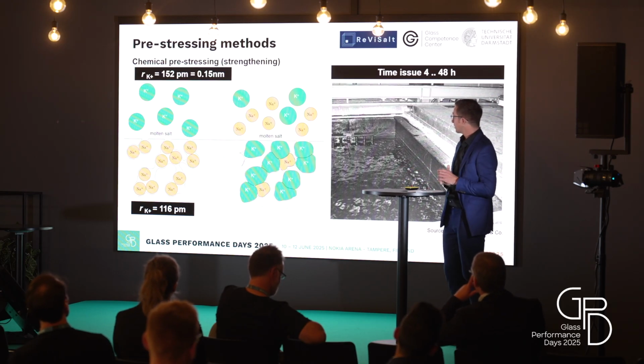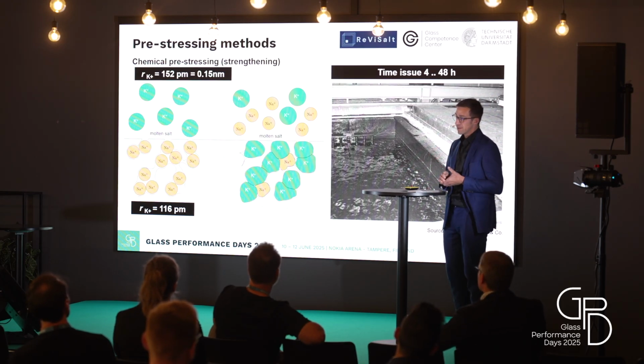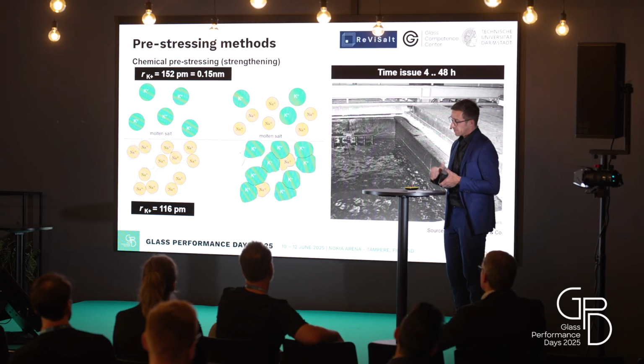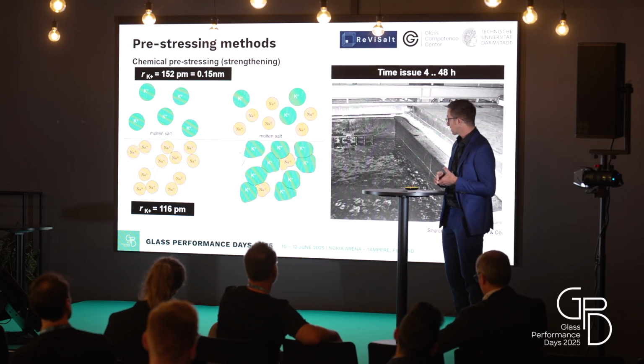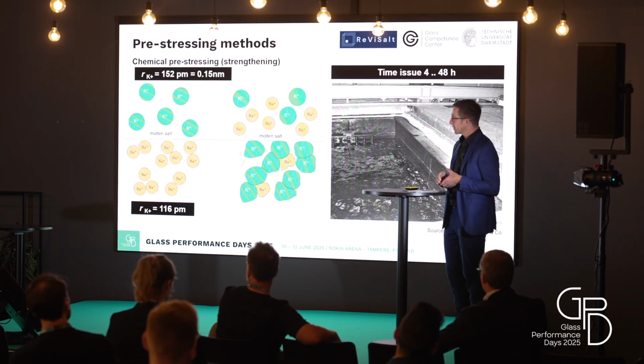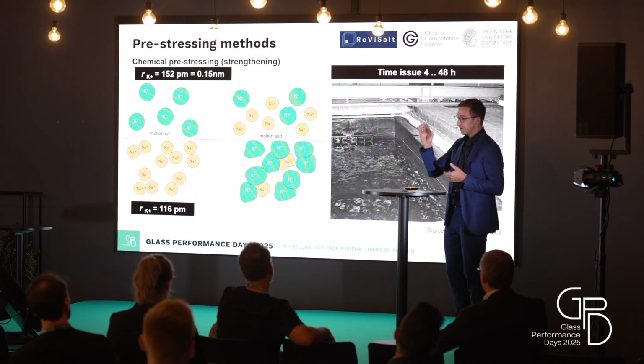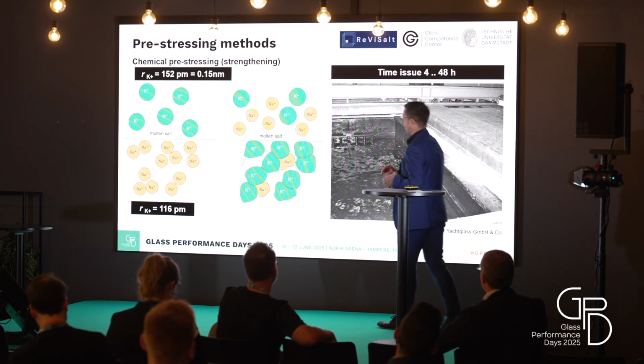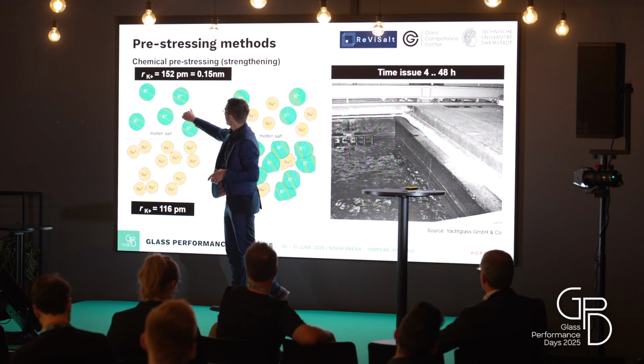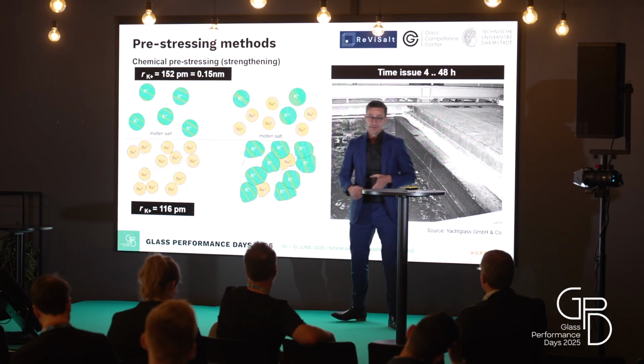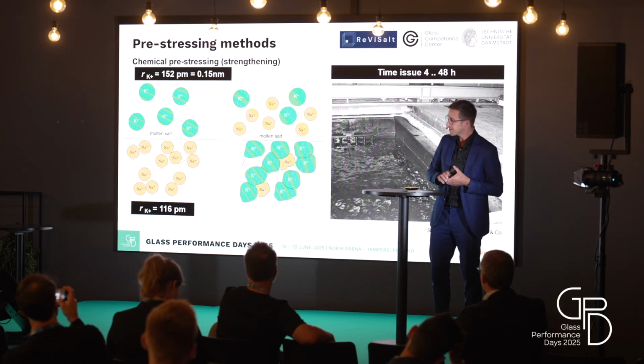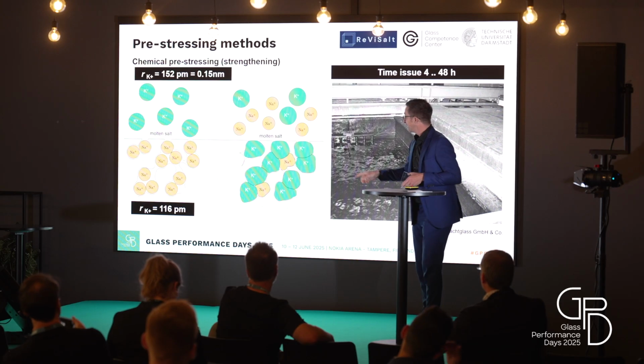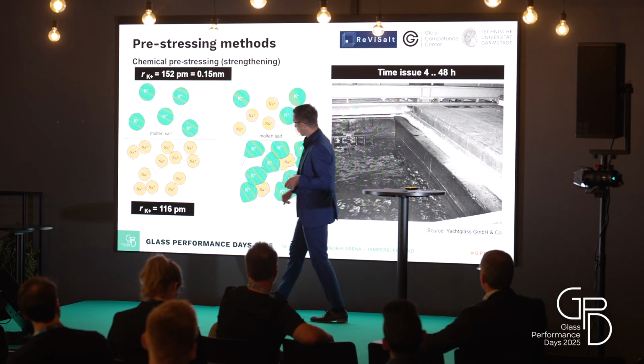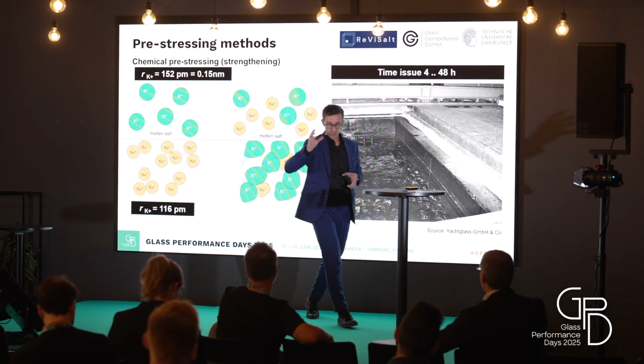This is the chemical tempering process. It's used more or less for the displays, also for the yacht companies or the windows of the yacht glazing. What we do there is an ion exchange process. We have the glass, we do it in a bath, and we have the really big ions here of potassium, 152 picometer. It's really big, but we have here the small one, the sodium, and this is the exchange process.